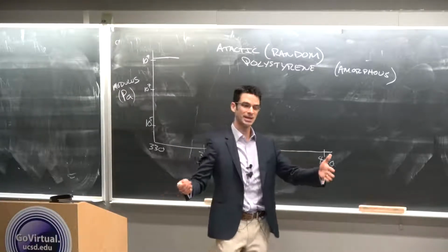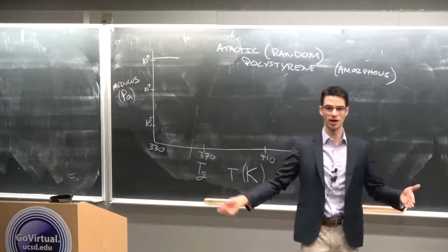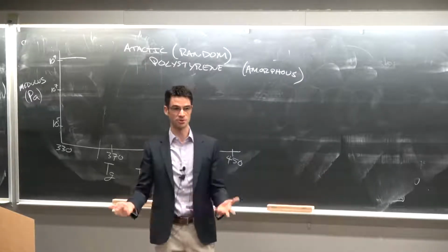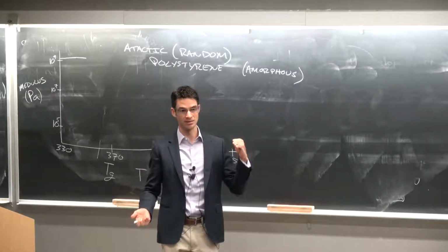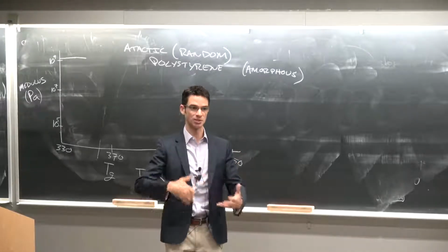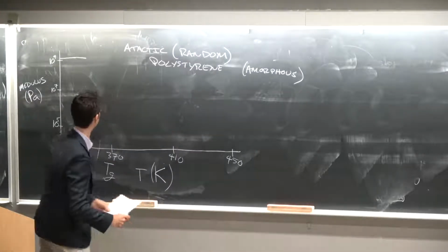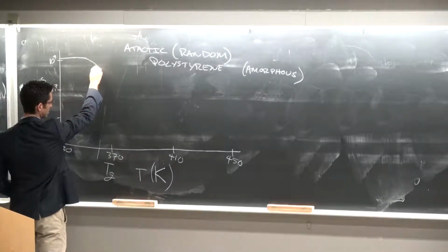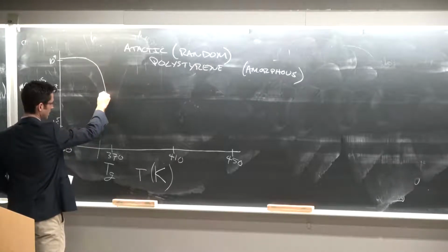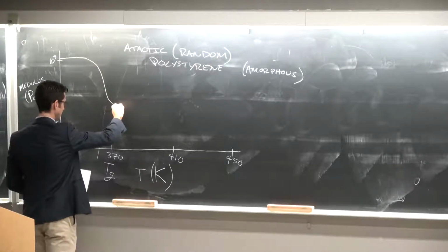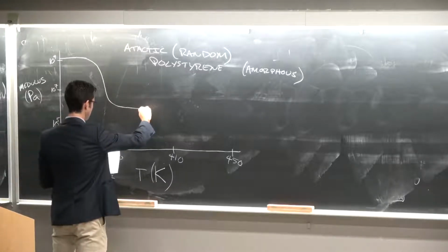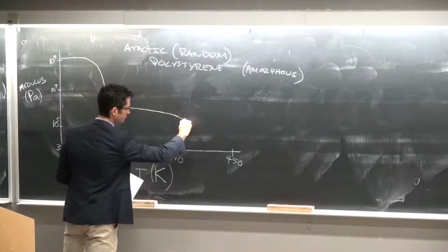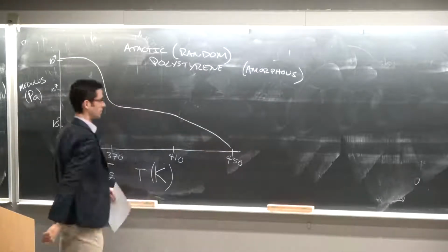So an amount of material at its boiling temperature requires an additional amount of energy to break all the bonds, and that's called the latent heat. And that's a first order phase transition. In the case of a glass transition, it's more of a gradual transition. So right in the vicinity of the Tg, it starts to go down, and then maybe it's here, and then you have this rubbery regime, then it's rubbery flow, and then it's a pure liquid.